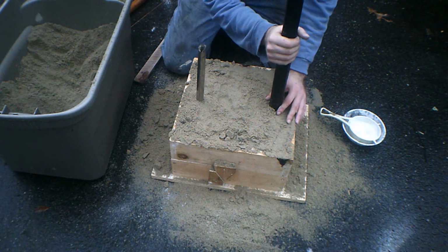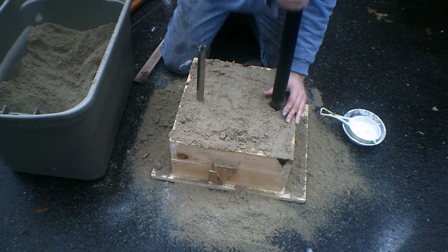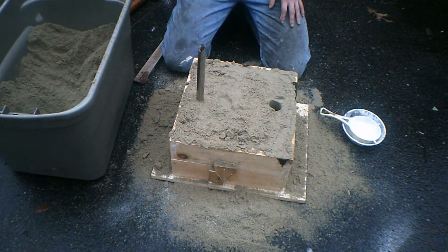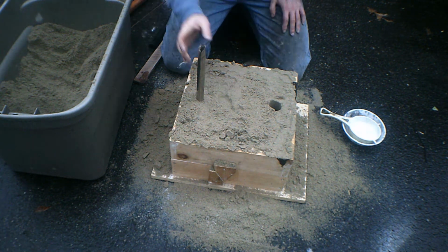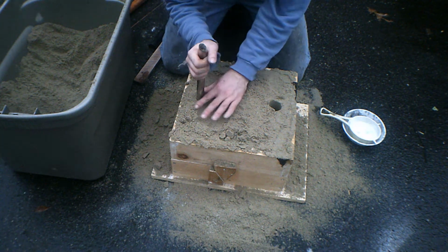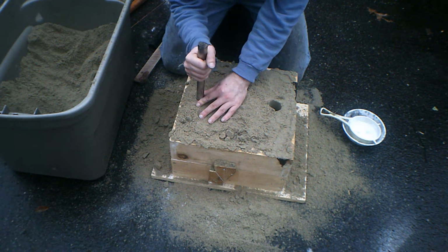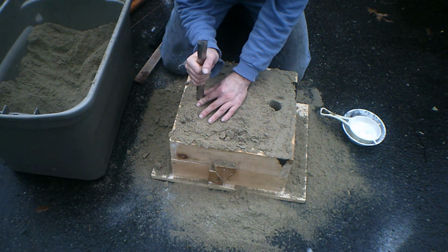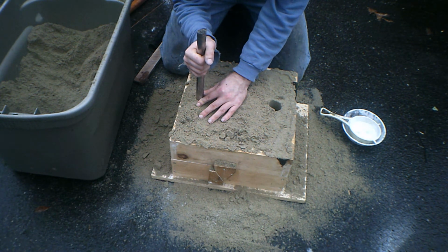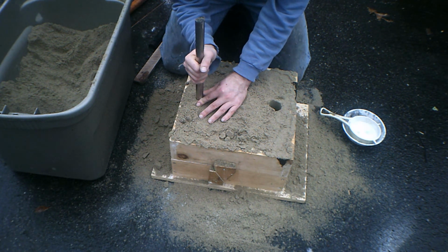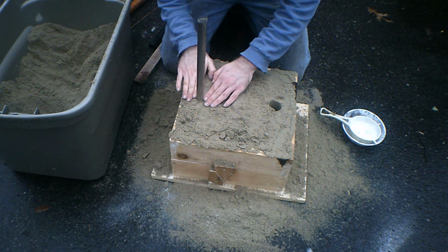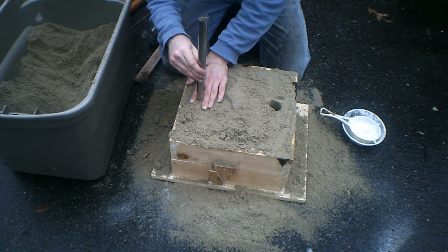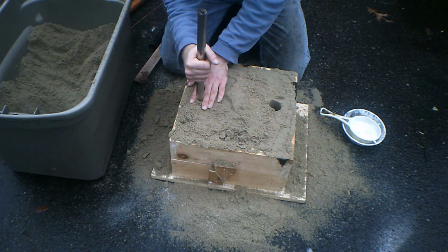And finally, the sprue and riser are removed. The riser can get wiggled around a little bit, but the sprue, ideally, you want to pull straight out so that none of the sides are damaged at all. So you should be able to twist and then pull. Now, the pipe that I was using has a bit of an out-of-round complication at the end, so I had some difficulty with this, and that may have weakened the cope as a result.